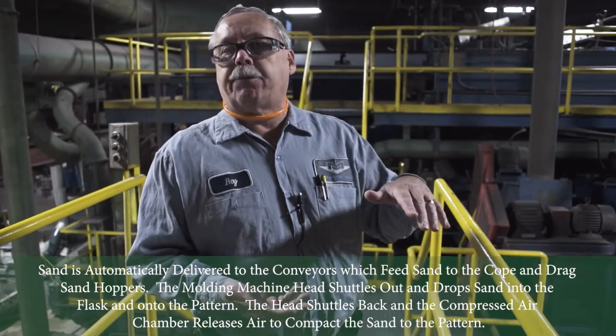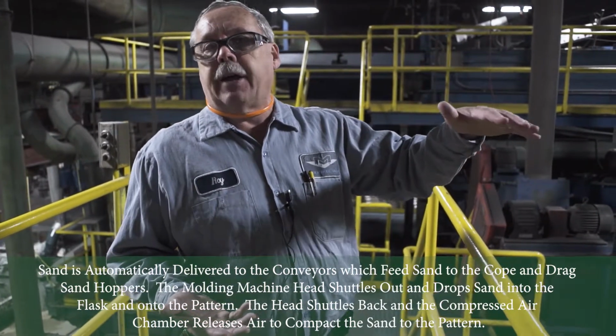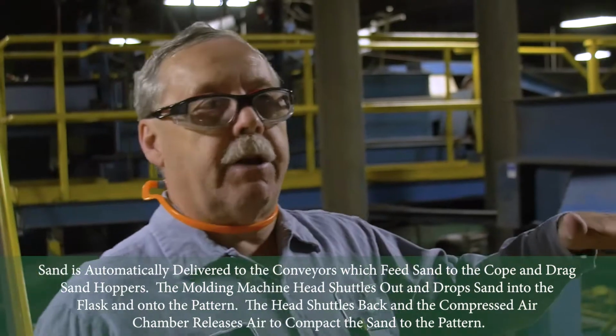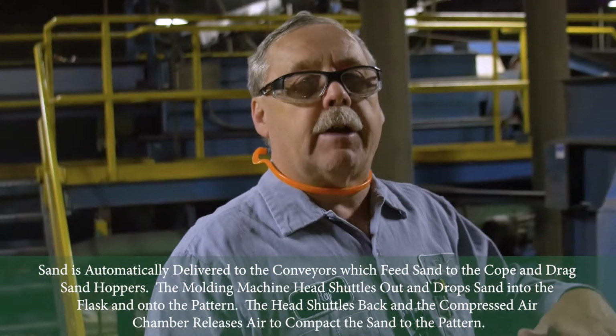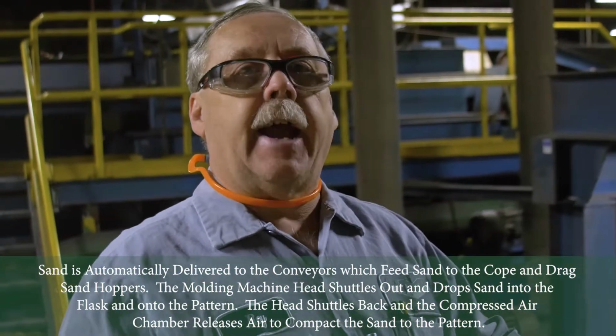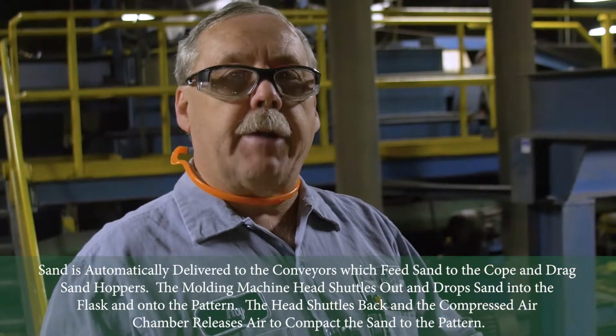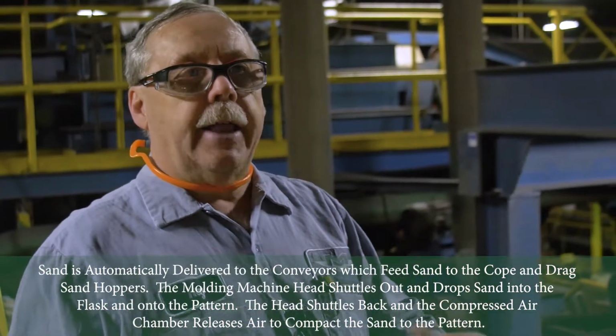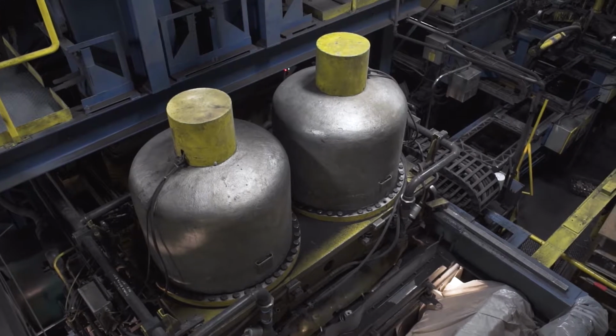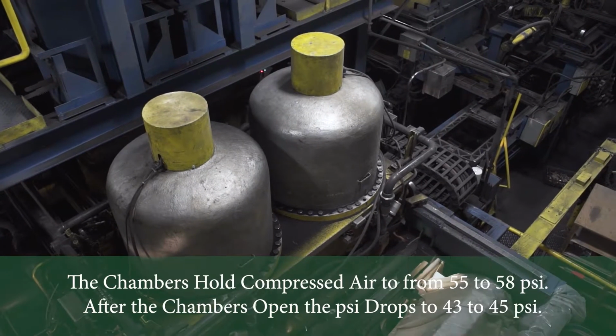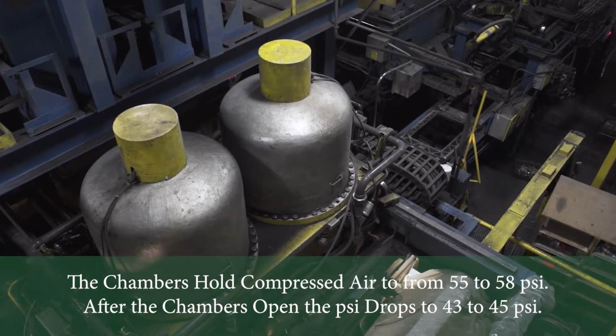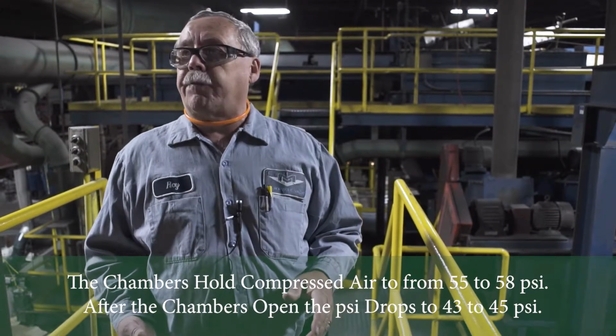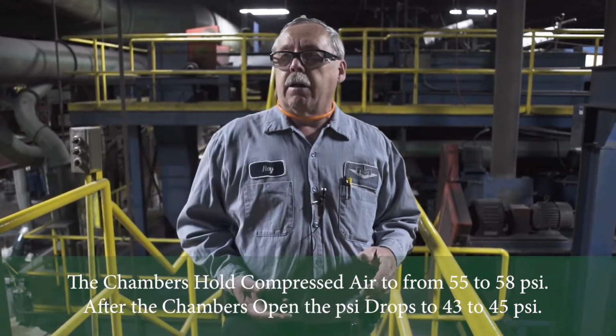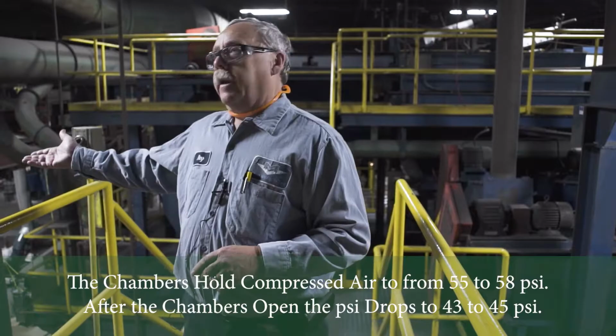That impact takes place with about 55 psi. It drops to 43 psi in a few hundredths of a second. It compresses the sand against the pattern to form the cavity in the mold, and then the further it gets from the parting line, the less dense it is, and allows the gases to get out of that mold when we pour the metal.